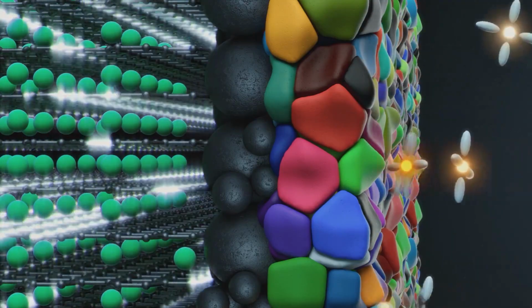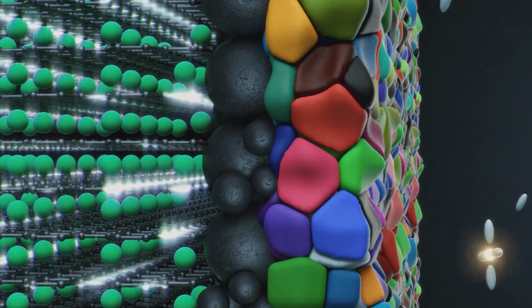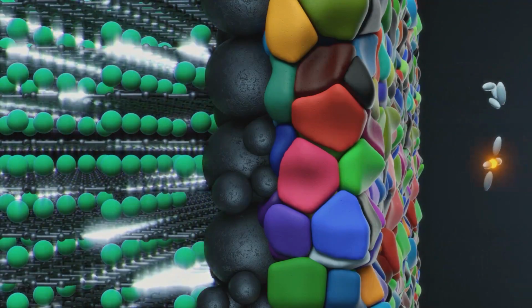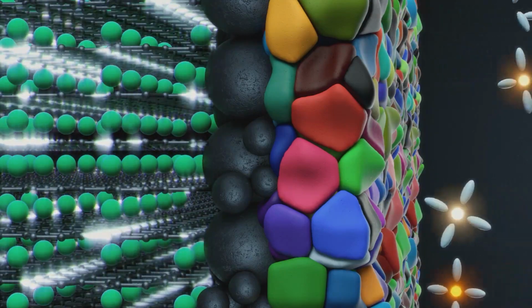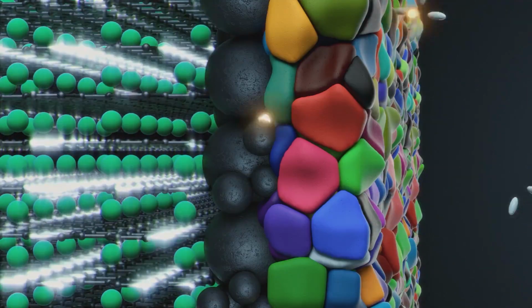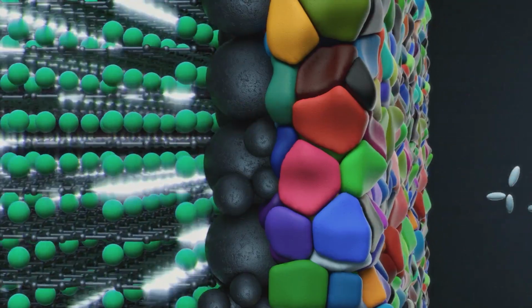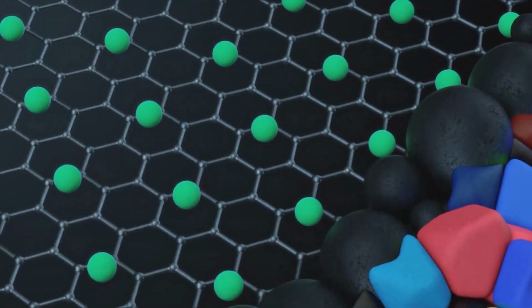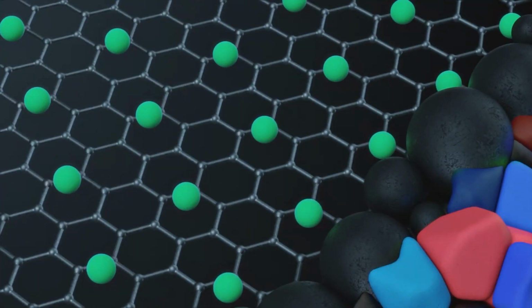The lithium atom sits between the layers of the graphene that make up the graphite. This is called intercalation. Electrostatic forces now hold the lithium atom in place. The lithium is stored at 1 lithium atom per 6 carbon atoms because this is what is most thermodynamically stable. The battery is now fully charged. Highly reactive lithium atoms are now stored in the graphite.